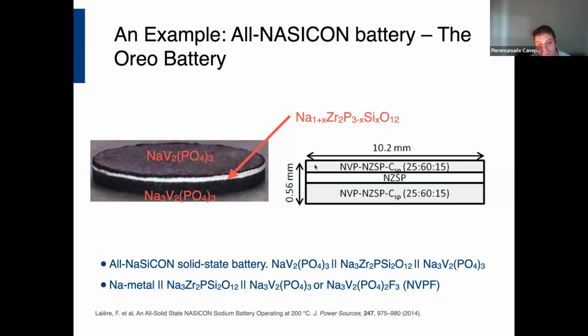And the interesting part of this all-Nasicon battery, whereas, as you will see, it will have a very limited energy density, is that because you get to work with Nasicon on all the three different layers, the two parts of the biscuits and the filling cream in between, the lattice mismatch is really reduced, since all these Nasicon share similar crystallographic features.